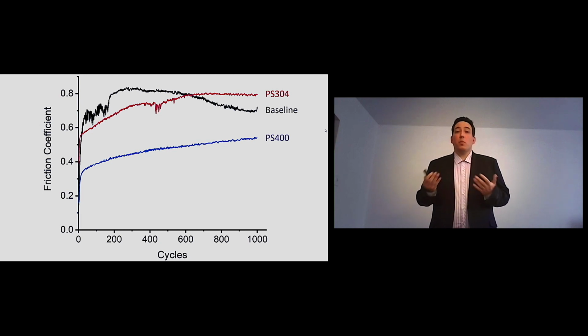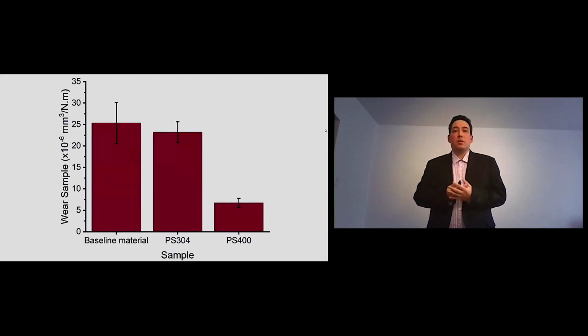Now we need to check wear, right? We want friction and wear. When we did the wear test and we observed the cross-section, what we see is that the PS400 showed less wear than the other materials, almost five-fold the baseline that we had, which is really promising. What I want to do now is understand why this material is behaving so well and try with different loads, different speeds, and different temperatures to replicate the conditions faced by the engine before we can put it there to work.